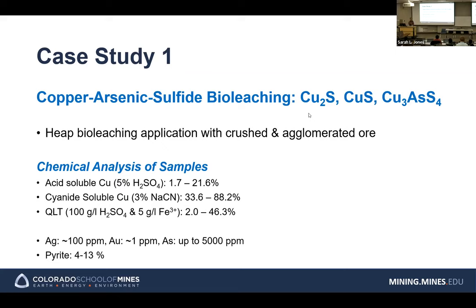It's very difficult to extract. So this is a heap bioleaching application with crushed and agglomerated ore. We ran this bioleaching test when I worked for a company, and the result was really good, so we built the demonstration plant. Chemical analysis of the sample: acid soluble copper anywhere between 1.7 to 21%. That means if you use sulfuric acid, we can get only up to 21%. So we cannot run just an acid heap leaching, because covellite, enargite, and a little bit of chalcopyrite, we know those are not really soluble in the sulfuric acid.